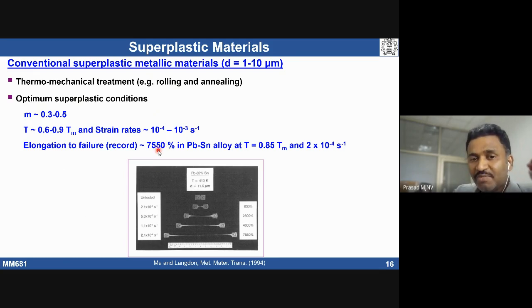So far, I think we already mentioned that a record percent elongation has been observed in a lead tin alloy at a temperature, look here, of 0.85 times the melting point, a very high temperature. And the strain rate is very low. This behavior is observed at high temperatures when the grain size is between 1 to 10 micrometers, and the strain rate is also very low.